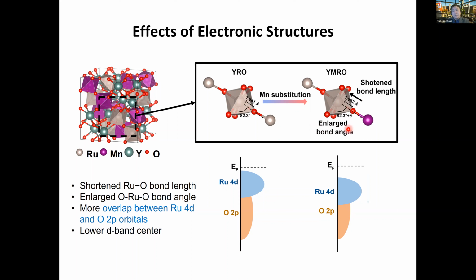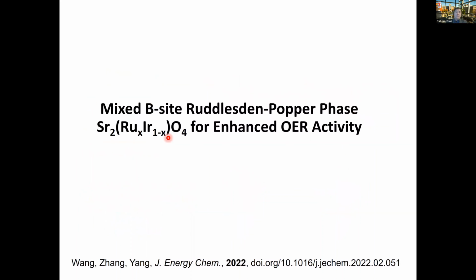Those two factors, in the previous study, demonstrated that potentially you could have this downshift of the ruthenium orbitals, and that leads to a better overlap, and this actually leads to a better performance in this particular system. So this is primarily based on a previous study and a hypothesis based on the XPS data, the XPS study that we have.